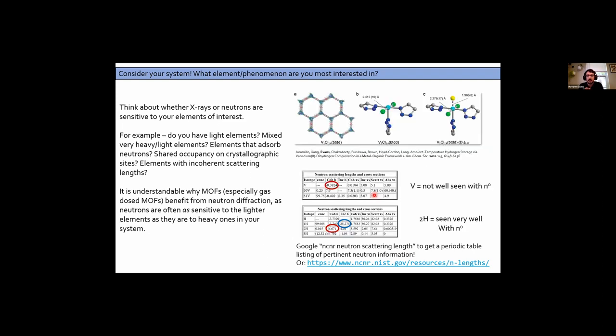So the example I'll show is, Craig mentioned we used a vanadium MOF. For those of you who've done neutron diffraction experiments, you'll know that you're putting the sample into vanadium cans and sealing it up. That's because vanadium is essentially invisible to neutrons, right? So trying to understand what's going on with the vanadiums from the neutron diffraction is a bit of a lost cause. And so we had to do complementary X-ray diffraction and do some joint refinements with the neutrons and the X-rays, to understand not only what was going on with the framework itself and the deuterium that we put in, right? So this has almost as large a scattering length as carbon, to understand what was going on with the entire framework together, right?